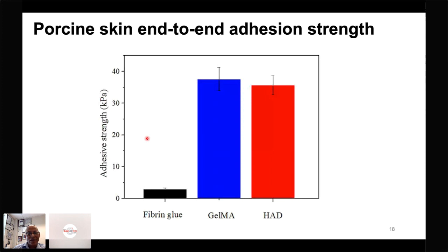And so this is an in vitro test where we took a porcine skin, and it's an end-to-end adhesion strength test. Basically, attach two pieces of porcine skin using this glue, and then you pull it apart after a given period of time, and then you measure the strengths in terms of pressure force here. Fibrin glue, we used it as a control because that's the gold standard that's clinically used now as a surgical glue. Gelma, because it's been reported in the literature to have some excellent adhesion strengths. And then this is the hemostatic adhesive, which is HAD, our formulation.